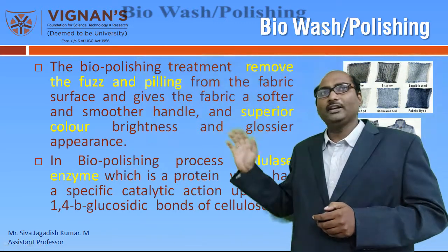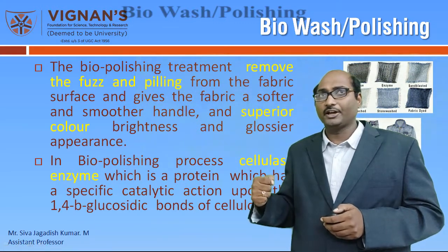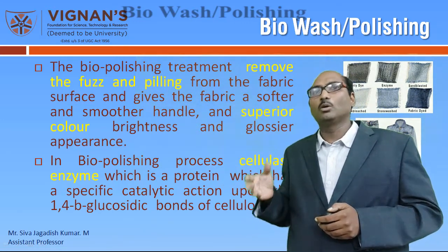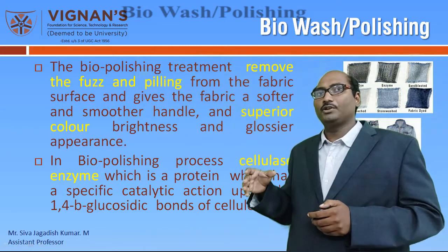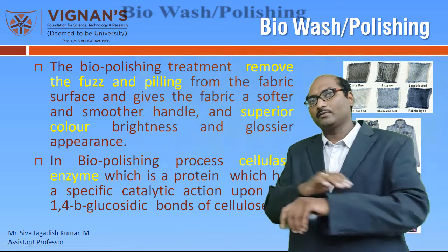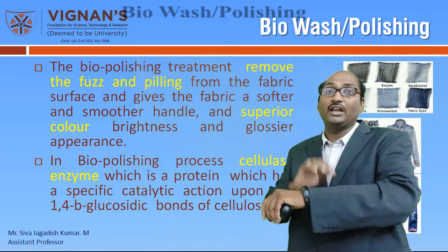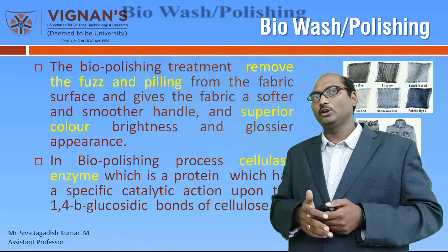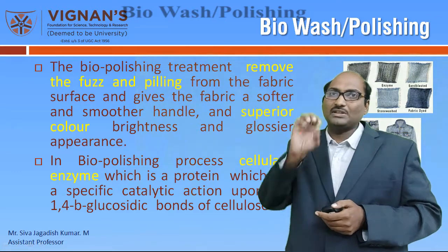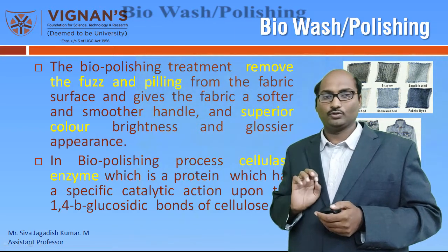I hope you now understood the difference between enzyme wash and bio wash. In biopolishing the objective is not to remove any color. Less concentration is used for bio washing, but in enzyme wash more concentration is used. In biopolishing or bio wash, it will remove the fuzz and pills so that the fabrics become smoother and superior color can be obtained. And in bioprocessing, the cellulase enzyme has a specific catalytic action upon the 1,4-beta glycosidic bonds of cellulose.